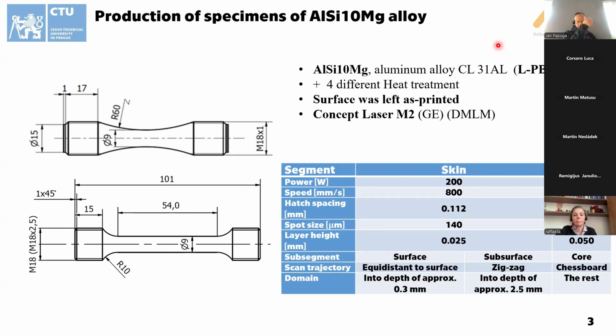In this presentation, I will present 4 different heat treatments. All the specimens were left as printed with no additional machining to the active part and the active cross-section of the specimen. We used a conventional hourglass specimen for the fatigue test, and on the lower part you can see the tensile test specimen, both of which have the diameter in the active cross-section of 9 millimeters.